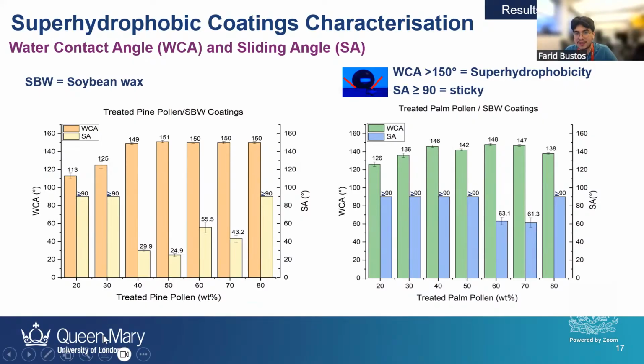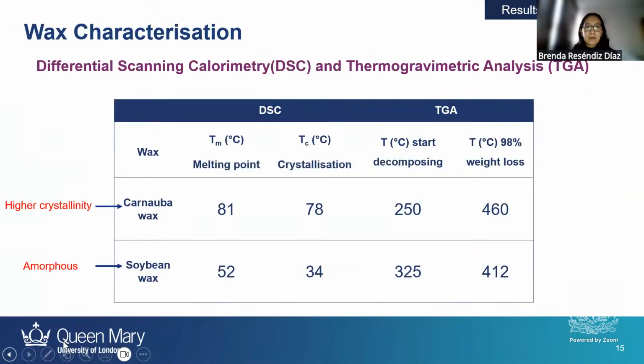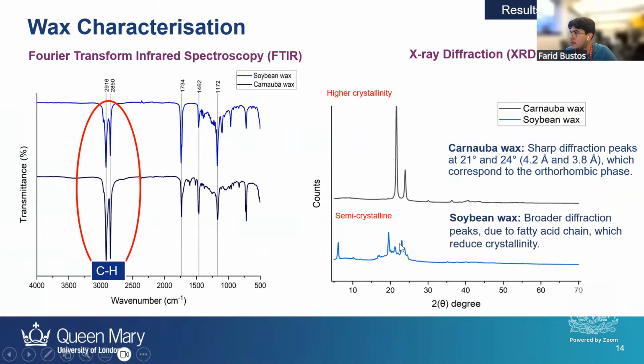I've got a couple of questions myself. Brenda, the first one would be, there's a difference between your two wax samples. One's a little bit of a crystalline sample, and the other one, as you said, is amorphous. I can see that there is some relationship between these two, that the Carnauba wax shows a little bit more of an ideal water contact angle and sliding angle. Do you think this has to be solely because of the crystallinity, or it's also a matter of coupling the wax with the pollen sample?